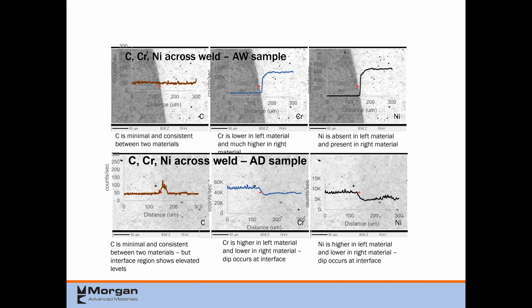So I did find it, and they were expecting to see that there was a sharp increase in carbon at that weld. And that's what you can see on the bottom left, is that there is an increase in carbon at the weld area, and that the chromium and nickel vary not as much, but as expected between one material and the other.